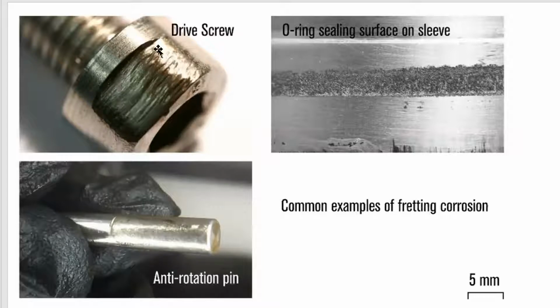If you were to look at the core, obviously you can see that this began to key in to the driver slot. And that driver slot, sure enough, had a dark area that was fretting corrosion. But you can also see that now, not only at the contact surface, but now this wall and the corresponding notch, this is probably maybe 10 or 15 thousandths deep. And so you'll see it on the corresponding part.